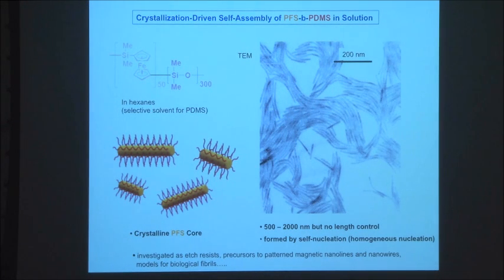And the way we look at this process is that when you dissolve the block copolymer in THF and then add hexanes, the hexane starts to precipitate the PFS block, and at some point you induce crystallization, and so this is like a self-nucleation process or homogeneous nucleation. And then once you get crystals, this drives the self-assembly through to give you cylindrical structures. And the formation of the crystals can occur at any time. It can be quite slow, it can be quite rapid. And so these cylinders will start growing at different instants, and they grow until the block copolymer is used up. And so you get different lengths because they start growing at different times. So this is our thinking on this self-nucleation process.